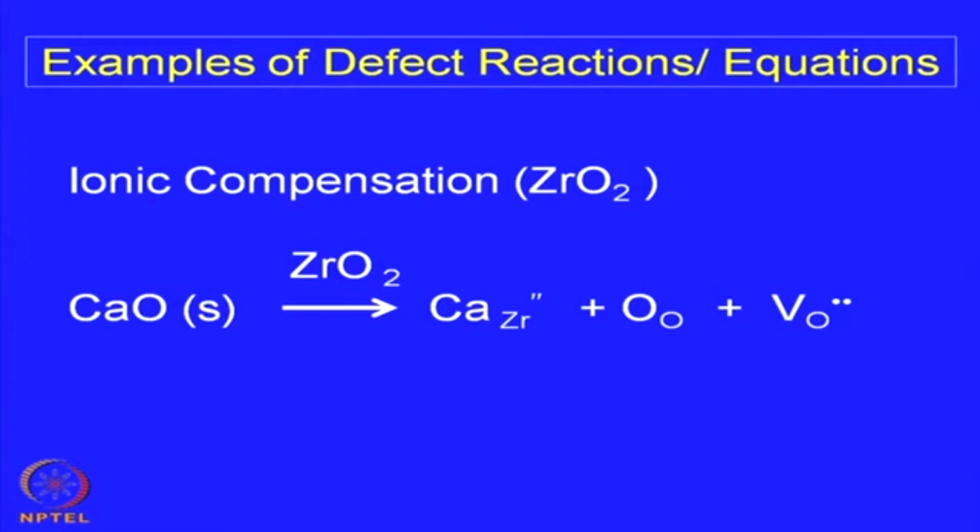Fortunately, in all oxides this can happen because oxygen is available in the atmosphere, and at slightly elevated temperature all these reactions can take place. There is a gas-solid reaction. So, oxygen can exchange between the solid and the environment. It can go in or go out quite easily, because oxygen is available in the atmosphere and also within the solid. If the kinetics is favorable, oxygen can exchange between the atmosphere and the solid.